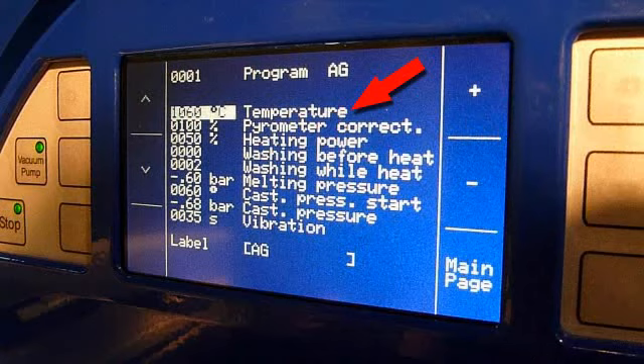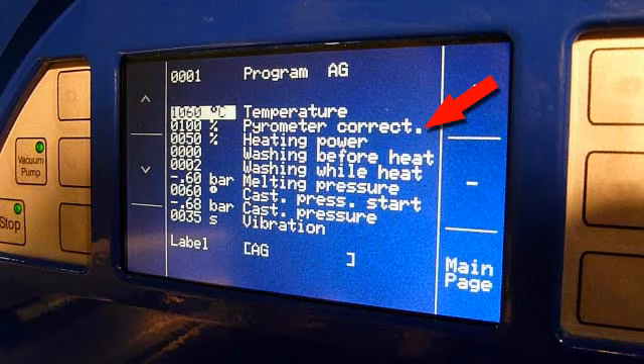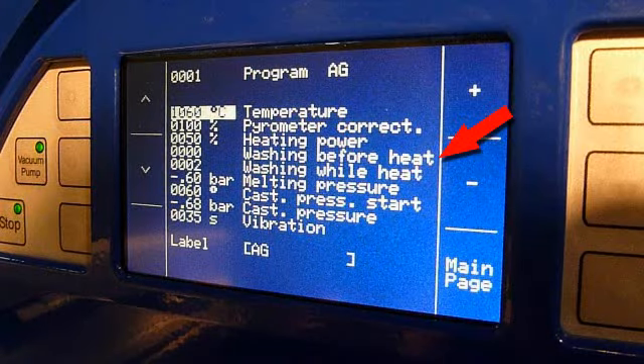The first parameter is the temperature at which you want to cast. In this case, we've set it at 1060. The second one is the pyrometer correct indicator, that shows that the pyrometer is reading accurately. The third one is the percentage of power that you want to use for the melt. The next one is if you wish to do washing before the heating, a wash cycle.